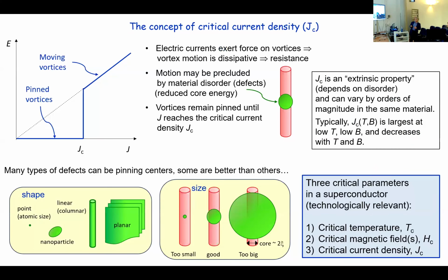And then finally, the third concept that is important is the critical current density. When you have vortices in a superconductor and you apply a current, the vortices feel a force. The current exerts a force on the vortex. If the vortices move, that movement is dissipative because the core is normal and moves, and that dissipates. And that produces resistivity, kind of an ohmic resistivity. It's not ohmic in origin, but it's the same thing. And that means the zero resistance is gone, so that is not interesting and it's not useful. However, fortunately, there is a way to avoid that, and the way to avoid that is to introduce disorder, defects in the material.